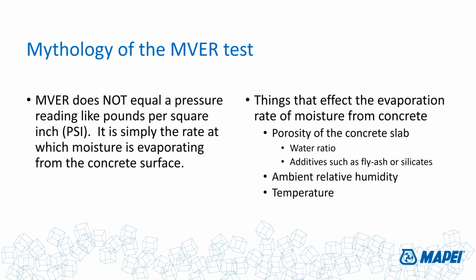And things that are going to affect that rate, and obviously things that they've tried to address in the ASTM F-1869 standard, are things like the porosity of the concrete slab. That's why they want you to do this test on an area that has been ground or opened up, as opposed to something that's highly polished and finished, so you get an idea what's underneath it, which I always thought was kind of weird, because you're not going to grind the whole floor, you're going to install on the burnished concrete. But okay, that's the standard that allows you to get to a consistent surface to work with, because burnishing and polishing all comes up with different rates of porosity.